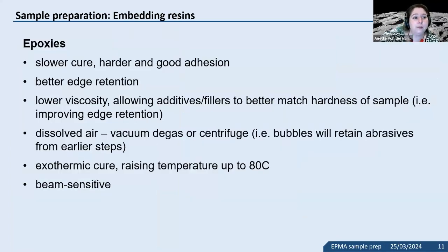There are different types of resins that you can use. Just a few words on them. Usually we prefer epoxies, but it depends a little bit on what kind of field you are in. Epoxies have good edge retention. That is important. We don't want gaps between the epoxy and the material, because then the samples can simply pluck out, and it also adds to charging problems, possibly. Ideally you want low viscosity for these epoxies, so that we don't create bubbles or pockets where the epoxy doesn't reach the sample.